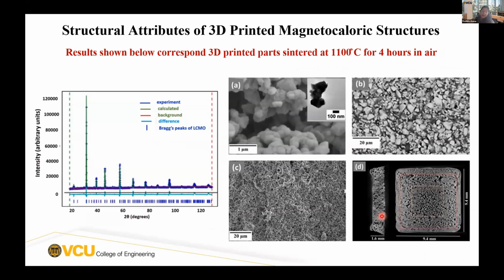With the LCMO samples, Webber has noticed that when you sinter the parts, he can get samples that have lost all binders but still have the crystal structure of LCMO. So there's no thermal degradation observed.